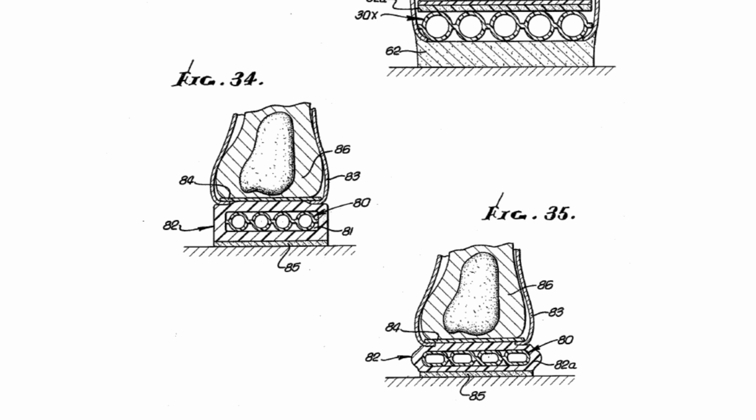While it is contemplated that numerous materials may be employed in making the moderator 32 of the improved insole construction of the present invention, several materials have been found to be particularly suitable, i.e., polypropylene, polyethylene, polypropylene-ethylene vinyl acetate copolymer, e.g., Profax SB 814, and polyethylene-ethylene vinyl acetate copolymer, e.g., Ultrathane 630. Other acceptable materials include Texin and similar materials. The thickness of the moderator may be between about 0.005 and 0.080 of an inch.